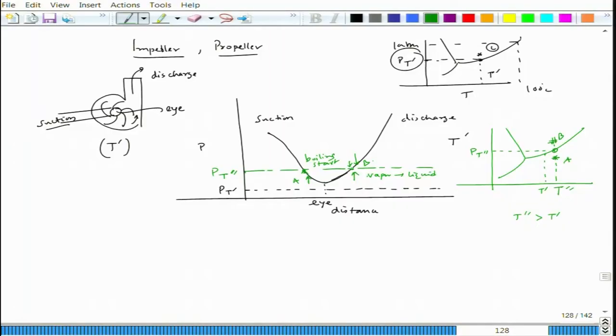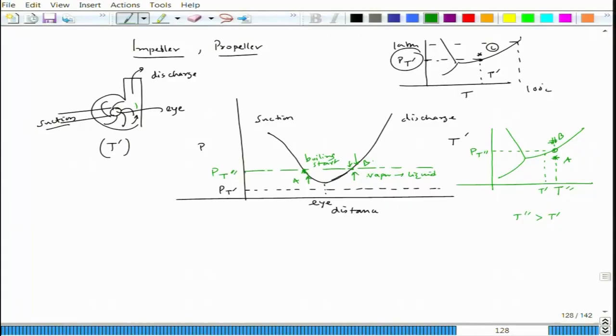So, now when it reaches the discharge location, those bubbles will collapse, and those bubbles are forming on top of the impeller blade, and then collapsing on top of the impeller blade. The bubble formation will be more if the impeller is moving this way; it would be more on the back of the impeller, okay. And this back of the impeller will have serious cavitation damage, and the damage mechanism is the same: impingement by a water jet due to bubble collapse, and then either passive layer formation, or the breaking of the passive layer and then repassivation, or it can deform the surface and then corrosion would happen. So, the cycle that I have shown will operate.